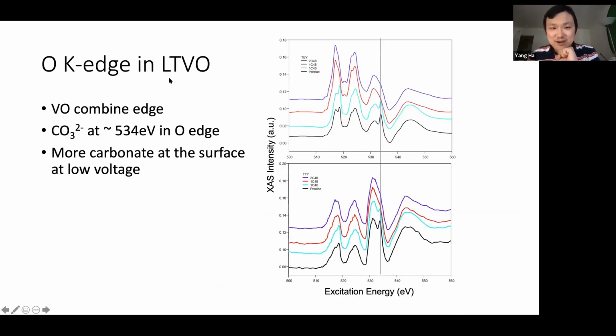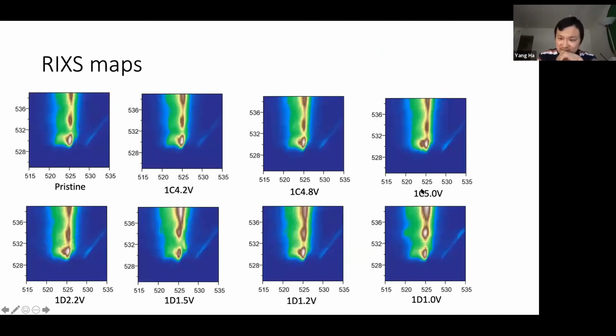So let's come back to our LTVO example here. The carbonate usually comes out at low intensity, and it's more pronounced at the surface, which has to do with the reactions between your electrode surface and your electrolyte, which is mainly organic molecule based. And what's more important is this feature, what we call the oxidized oxygen feature. In this cathode material where we have purely oxygen redox, we can see every time we charge our samples more and more, this feature becomes more and more pronounced. And once we discharge it, it vanishes.